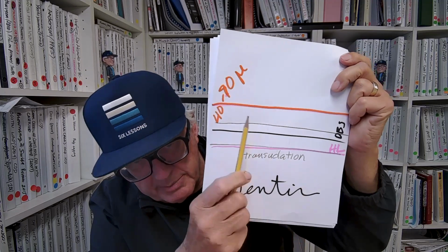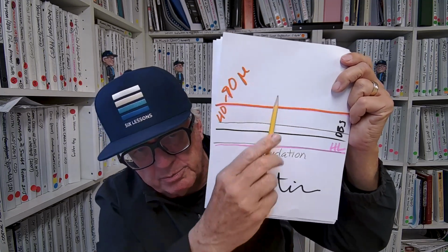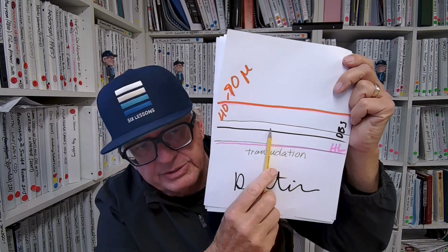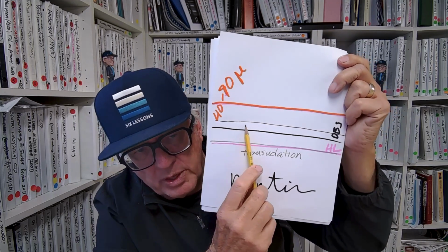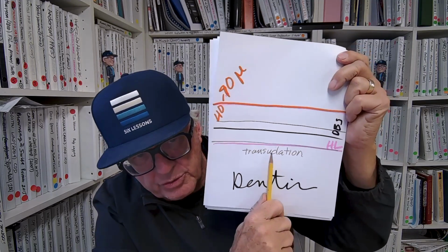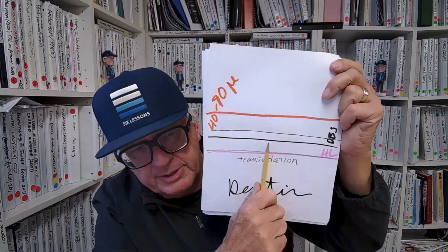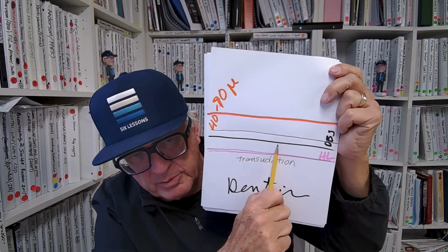So you're priming and you're bonding, but if this layer is too thin when you put the light on it, this does not polymerize because oxygen has quenched all of the camphorquinone molecules. And so the transudation keeps coming up into this area, and you have just a gooey mess that doesn't polymerize.